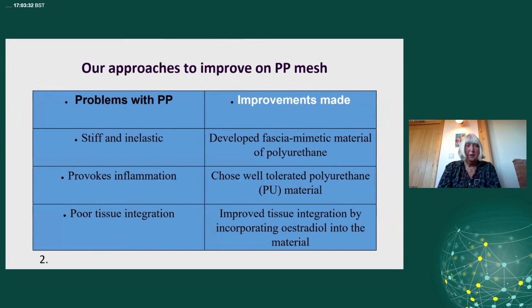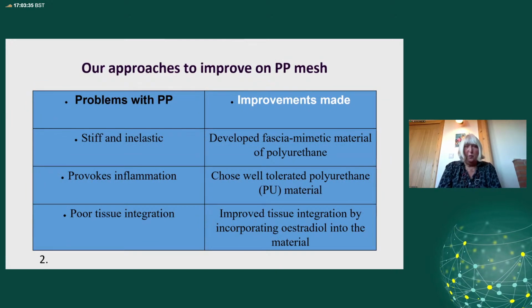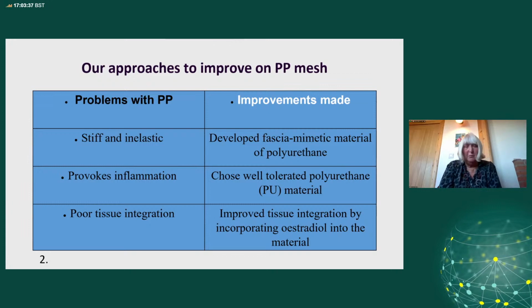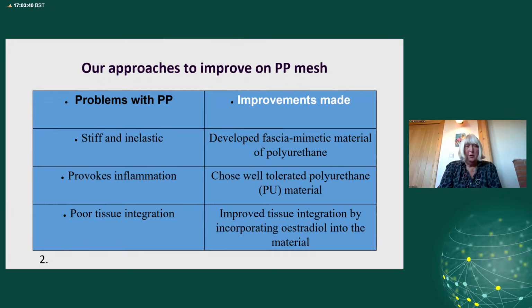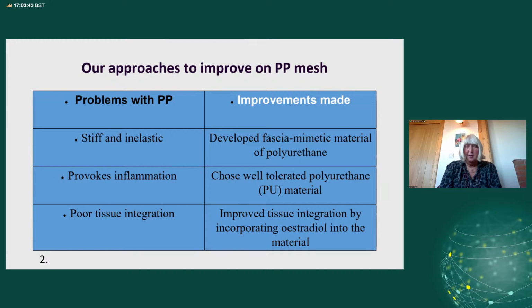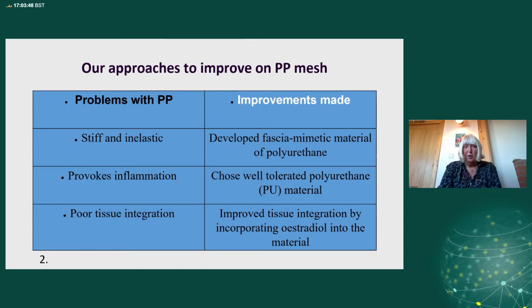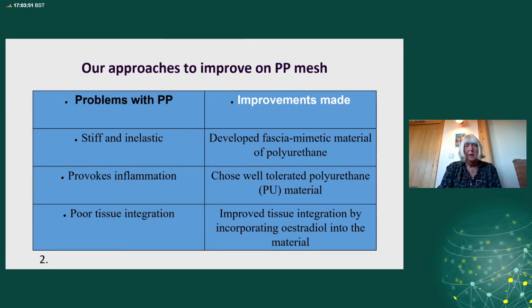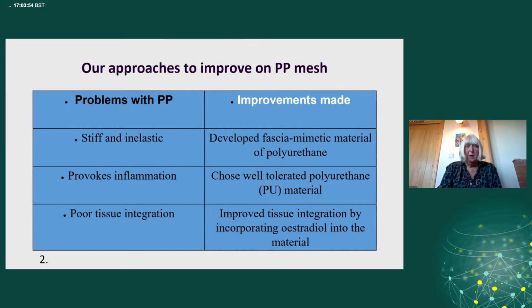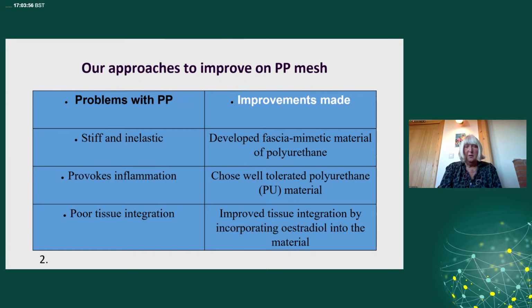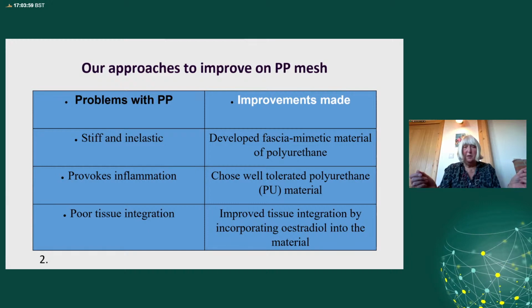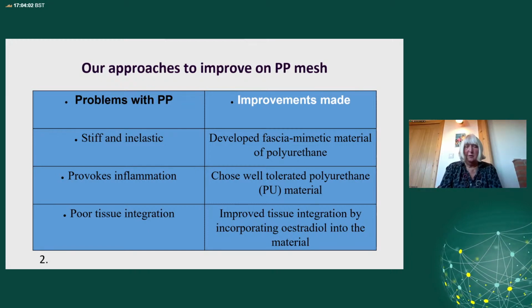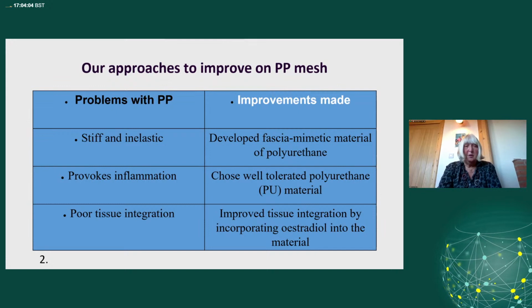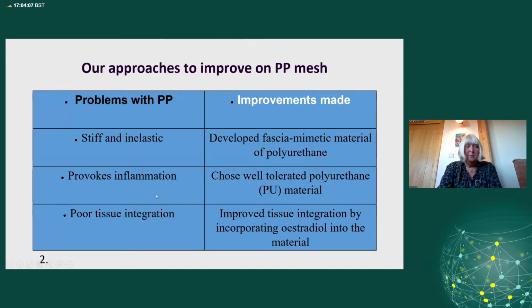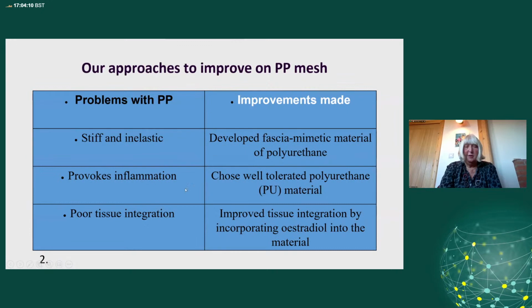So arguably, this is what we need: a biomaterial that mimics the mechanical properties and tissue integration of fascia. So the problems with polypropylene: when we began working with Chris on this, probably some 8, 9, 10 years ago, we concluded that polypropylene was too stiff and inelastic for the job. And we developed a fascia mimetic material made out of polyurethane. Now, I'll show you a picture of this shortly, but it's an electrospun material in which we've put 3 layers together, consisting of an aligned layer in the middle of the sandwich and 2 random layers either side of it, all joined together.